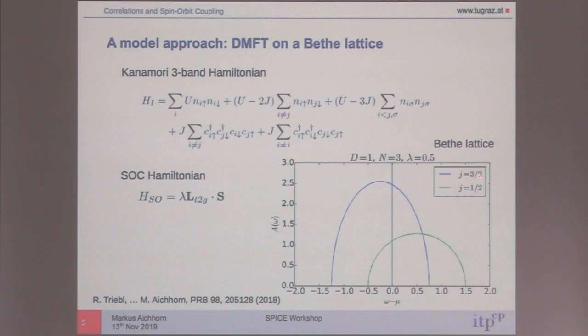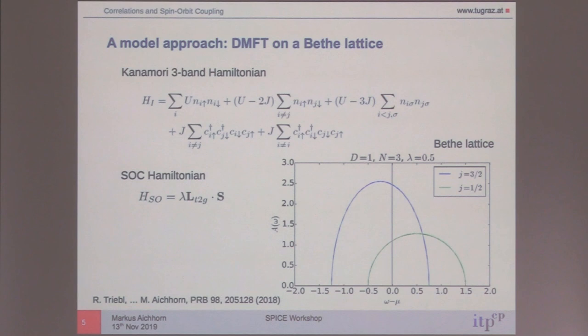You have two orbitals — one labeled J3/2 and one J1/2. By spin-orbit coupling, one shifts down and one shifts up. But there is not an immediate gap — the gap occurs only if the spin-orbit coupling is large enough to overcome the bandwidth. This is sometimes forgotten: spin-orbit coupling needs to be at some strength to fully polarize the system. This polarization will be important in what follows.